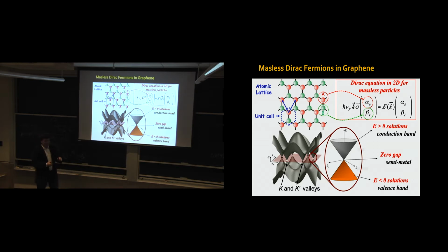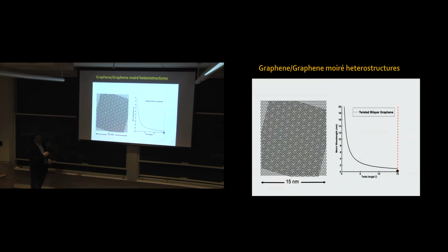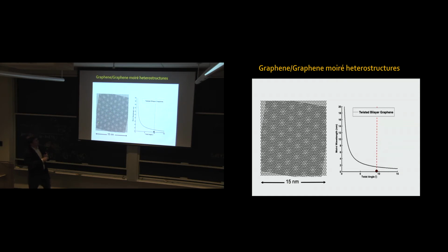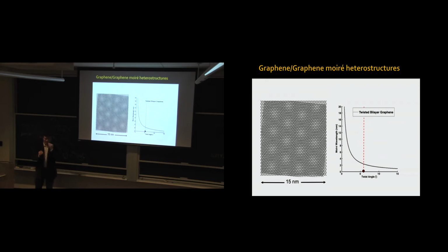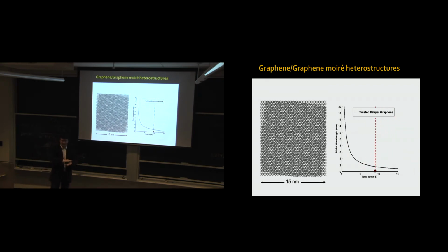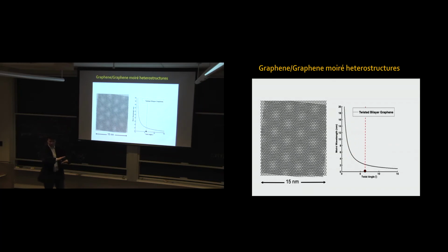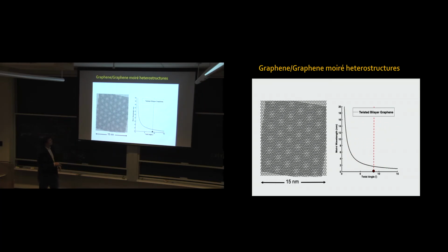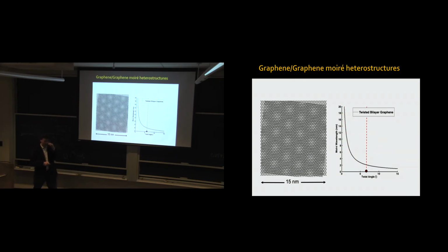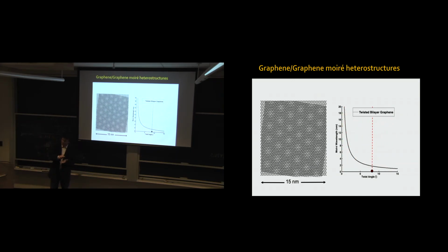Now, what happens if you put graphene on top of graphene and you rotate? You form a moiré pattern — a super-periodic structure when you put 2 periodic structures on top of each other at an angle. The wavelength of this moiré pattern is the distance between the soccer-ball-like patterns you see here, and that moiré wavelength depends on the angle of rotation between the 2 sheets. In the case of graphene on graphene, because these are 2 identical lattices, the moiré wavelength can go all the way to infinity when you align them exactly to 0. So this is what happens in real space. Let's see now what happens in reciprocal space, and therefore how the electronic structure is modified for this system.